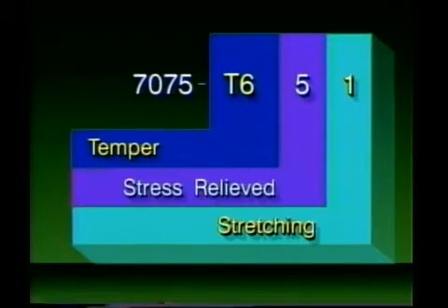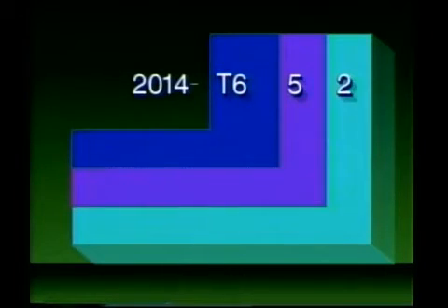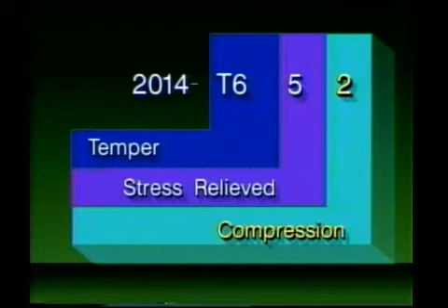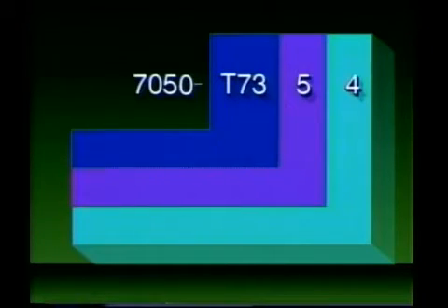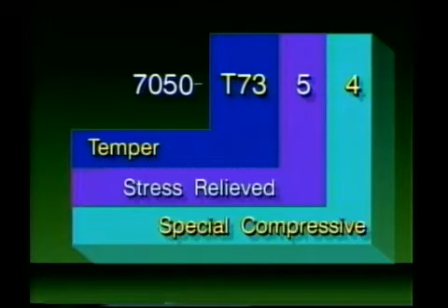The typical appearance of stress-relieved tempers would be the following: 7075 T651, alloy 7075 in a T6 temper, where the product is stress relieved after quenching by stretching. This temper is usually applicable to sheet and plate products and sometimes extrusions. 2014 T652, alloy 2014 in a T6 temper that has been stress relieved after quenching by compression. 7050 T7354, alloy 7050 in the T73 temper. The part is a die forging that has been compression stress relieved after quenching in the finish forging dies.